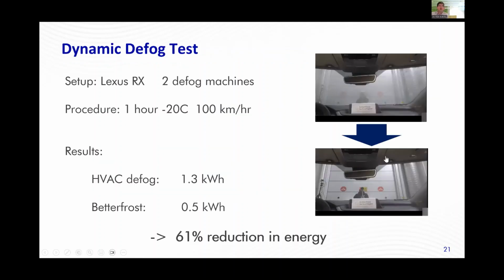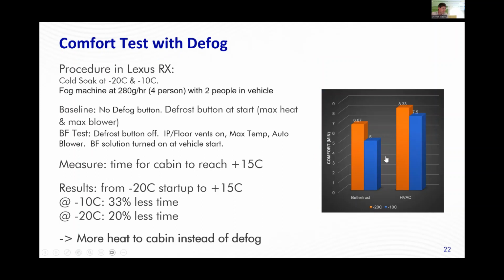So when we test to defog, in this case, this is a dynamic test at minus 20 C at 100 kilometers per hour. This shows the energy reduction compared to the HVAC system that was in the vehicle and our energy, here, a 61% reduction. Also, when we did a comfort test, starting from minus 20 C going up to plus 15 C, was 33% less time from minus 10 or 20% less time from minus 20. Again, this is a way to get more heat into the cabin instead of applying it to the glass.